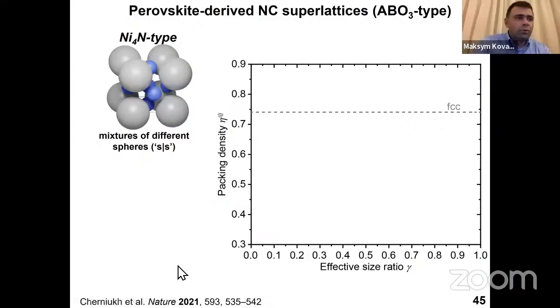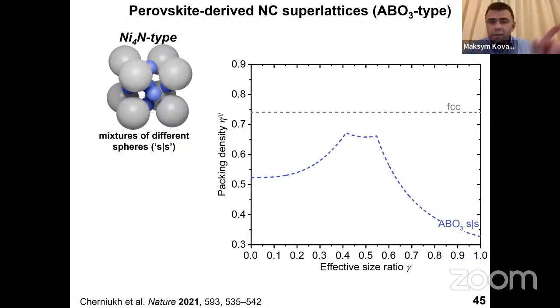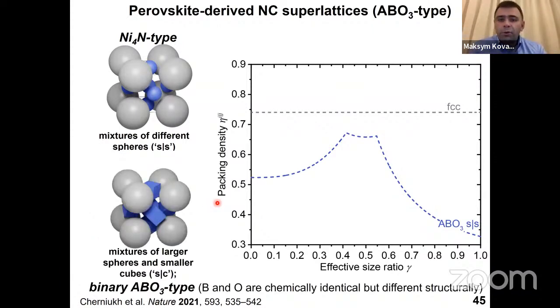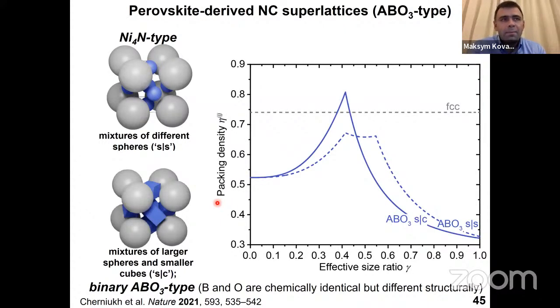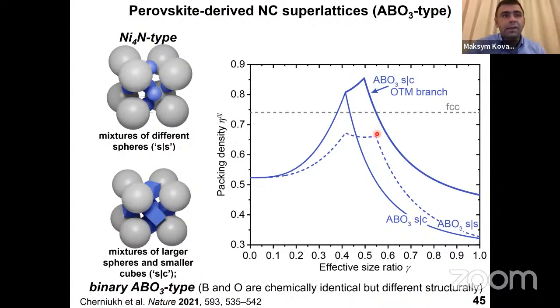All right. And if you compute the packing density at any size ratio, this lattice is indeed unstable. But now, when you mix a cube and a sphere, you do get the perovskite type lattice, because already without any assumption of ligand deformation, at least in some narrow size ratio, you have very high density. But if you assume in addition the ligand deformation, you will expect an even broader range of stability. And then we checked this range experimentally, and we indeed observed that cubes and spheres do form such a lattice,